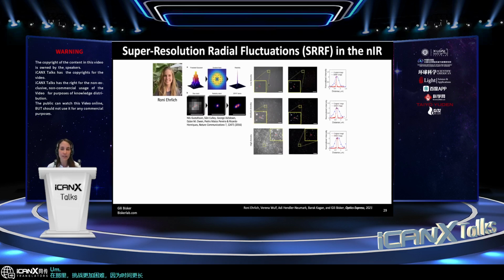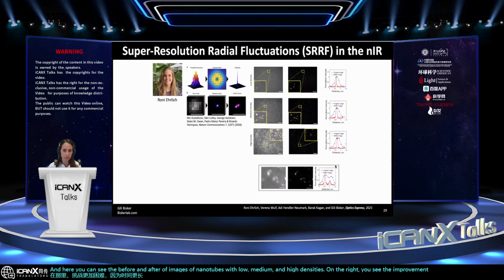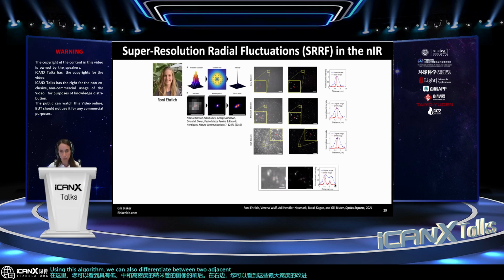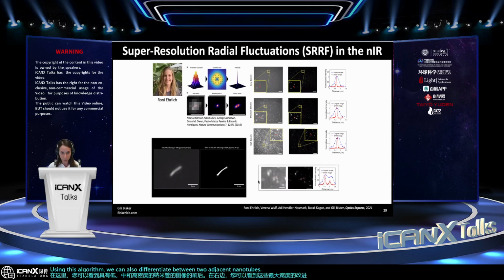And here you can see the before and after of images of nanotubes with low, medium, and high densities. On the right, you see the improvement in the full width at half max of these cross sections. Using this algorithm, we can also differentiate between 2 adjacent nanotubes, which we could not differentiate before. And we can also super resolve videos of single carbon nanotubes in solution.